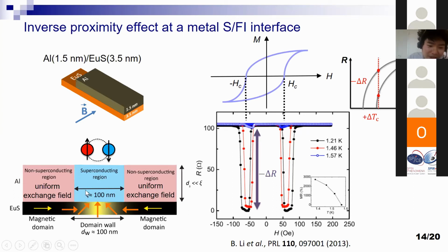So if this inverse proximity effect is strong enough, we can see a TC difference between here and here. So TC on domain wall and TC on homogeneously magnetized domain should be different. Professor Jagadeesh Moodera's group observed this effect using this bilayer structure.